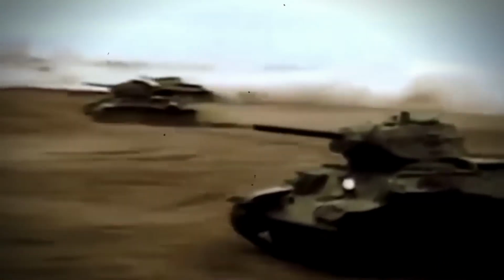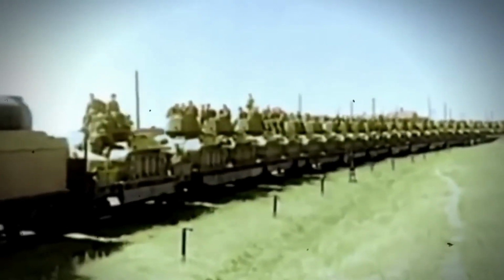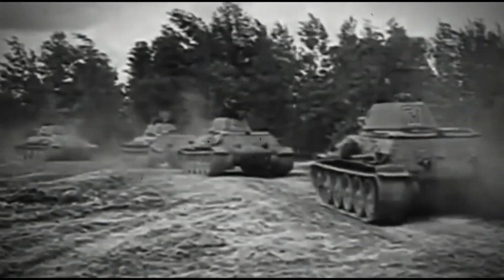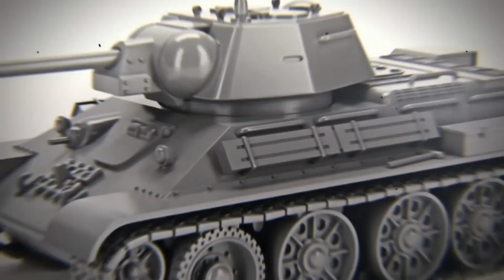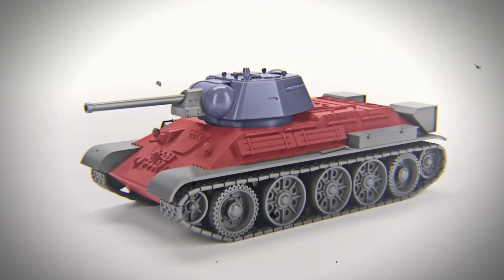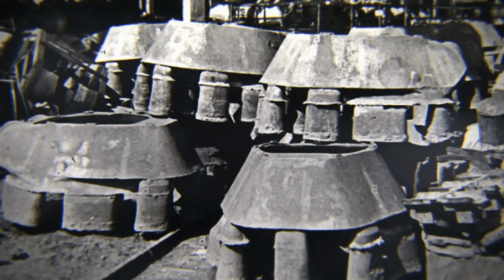It seemed that one could stop at this point. However, cast armor proved to be very convenient for the production of turrets and some complex-shaped hull parts. Unlike rolled armor, it does not require complex equipment for production, and the process is faster, which in wartime is very important. Moreover, casting allows manufacturing parts with variable thickness, which is very important for differentiated armor, for example, the same turrets. Therefore, rolled armor was used for the hulls, while the turrets gradually were converted to cast armor. This is how the cast turrets of the 1934 models looked.